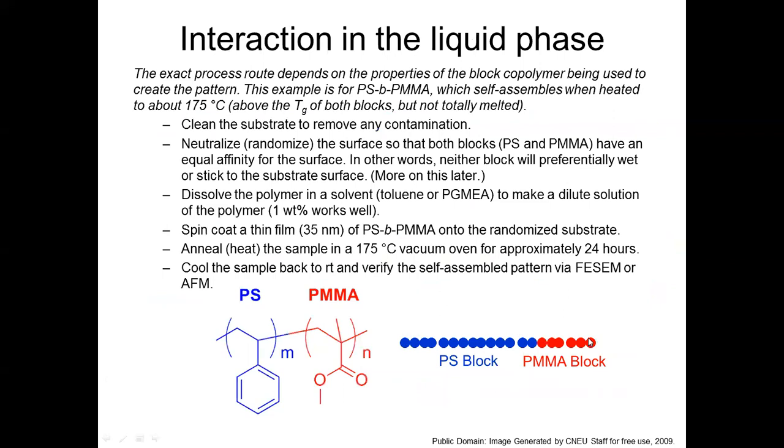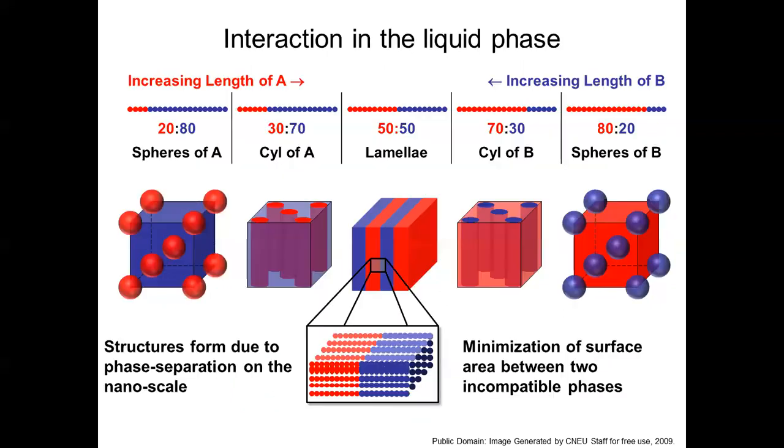So that's the relative thickness or thinness, however you want to look at it, of the material that we spread across the wafer. To have these well-formed geometries, we're only going to be able to have this height on the order of 50 nanometers or so. And we would also have to have an additional randomization layer on our surface so that these don't preferentially wet.